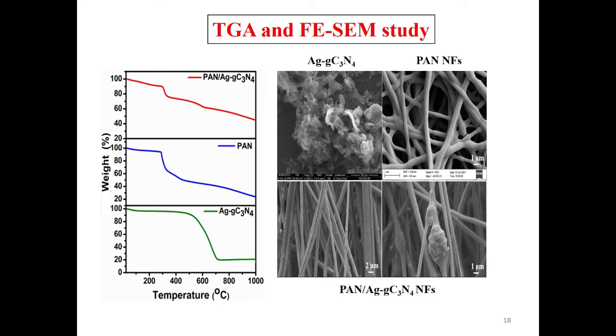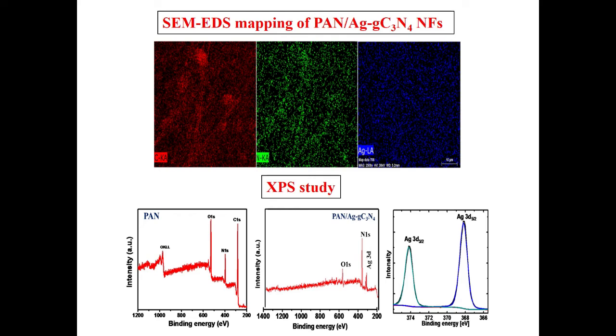But at one point there is a bead-like structure, where the fiber is getting knotted, and some coupling of the fiber is observed. This is because of the change in viscosity during the drawing, during the fabrication of that fiber with the help of the electrospinning technique. This is the EDS mapping of PAN/Ag-gC3N4. Uniform fibers are observed with a uniform diameter.